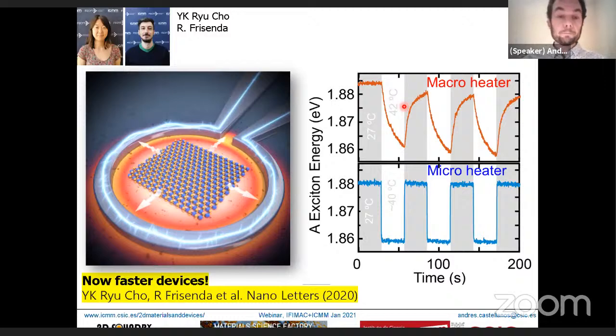For the speed, we thought: if a macroscopic heater takes a lot of time to thermalize, what if we make a microscopic heater and place our flakes in the middle of it? In theory, if the heater is smaller, it will heat up a smaller portion of the substrate and might be faster. Indeed, using these microscopic heaters we can reach much faster switching speeds—now around 10 hertz, basically 0.1 second—increasing the speed by a factor of 100 to 200.